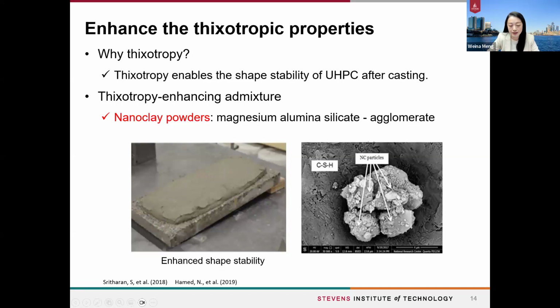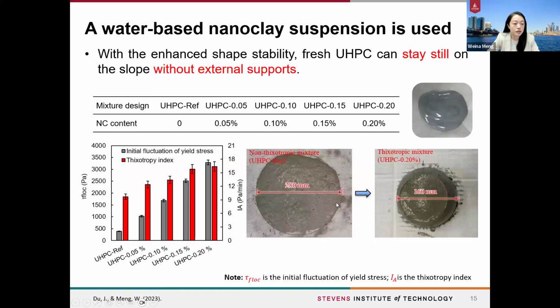The typical way to enhance the thixotropy is to use nanoclay powders. However, this method, as reported, has very severe agglomeration of those types of nanoparticles. These agglomerations will have a very adverse effect on the mechanical properties as well as the durability of the materials. So to avoid such agglomerations, we use well-dispersed, water-based nanoclay suspensions to enhance the thixotropy. As you can see, the thixotropic properties can be very effectively enhanced. So with the enhanced shape stability, the fresh UHPC can stay on the slope without external supports.